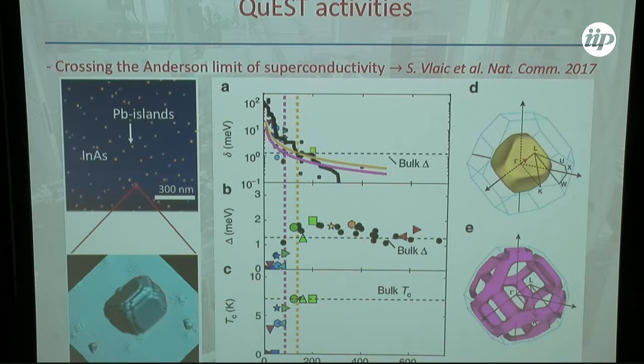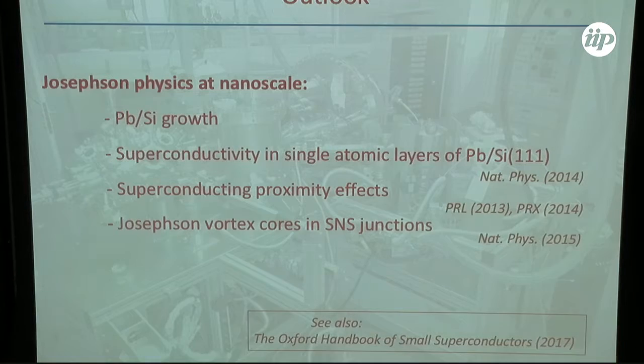And if you take just a simple model starting from Kf, because in lead there are 2 Fermi surfaces, you can easily see that interlevel spacing becomes about 1 milli-electron volt exactly at the same position. So you have concomitance of increasing of interlevel spacing with reducing the size and vanishing of the superconducting gap at the same edge.